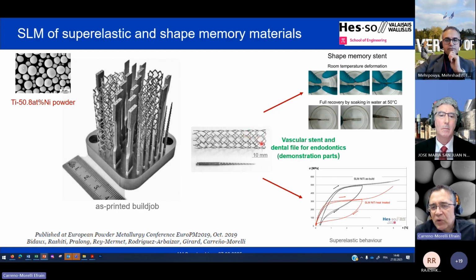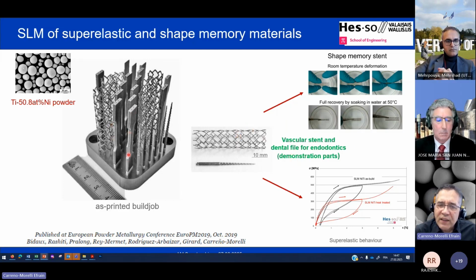And the geometry is quite similar to the original. Of course, the roughness condition is not proper and can be improved. And we also use a strut diameter of minimum 200 micrometers, 0.2 millimeters. Then we also perform tensile tests on dog bone shaped specimens. At the time, it was not common to perform tensile tests. All the tests on the additive manufacturing of titanium nickel alloys were mainly under compression because usually people are afraid about the cracks and the poor behavior, but we tested in tensile conditions, and we obtained